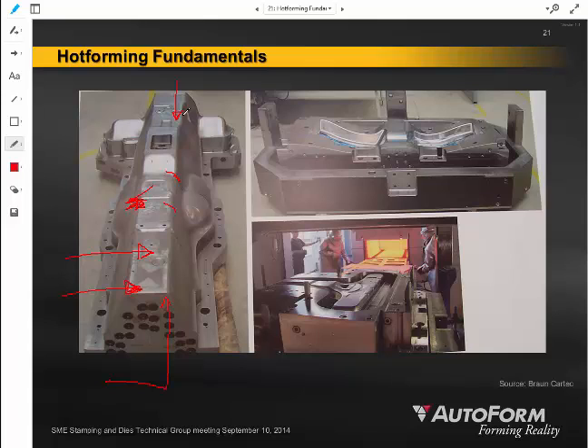and when that blank comes out, it's piping hot, and they've got maybe 4 to 5 seconds from the time it exits the furnace until they want it inside the press and forming metal before the material cools too much and causes different characteristics. So they have to plan everything for the instant it leaves the furnace until it gets loaded. How fast is the die closing? How long do we hold it closed? These are all things that have to be engineered well in advance and proven out in order to validate the product design and the product engineering decisions that they've made.